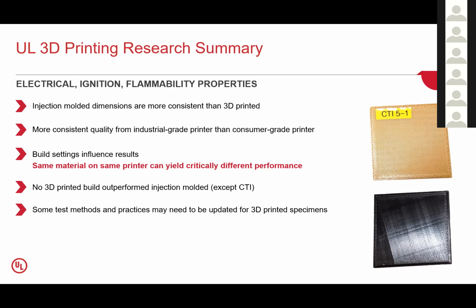In none of our tests did we see where the 3D printed samples outperformed our injection molded samples, with the exception of CTI, which, as I said, we believe to be an artifact of the test. So that's a nice thing to know, that if you are doing your testing and you're getting acceptable performance on a 3D printed prototype, moving to an injection molded one will be at least as good, if not better. So it's a nice place to be.